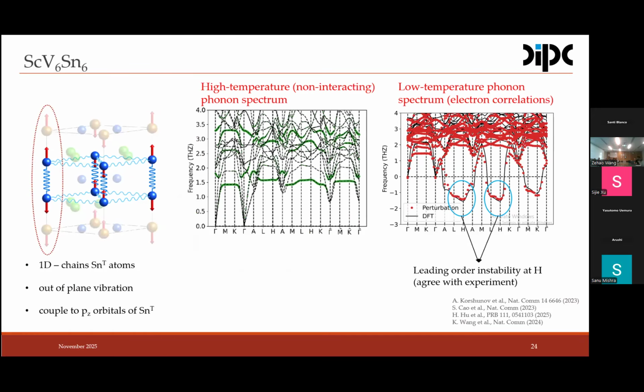We can put a bit of theory here, a bit of calculations by the group of Andrei Bernevig. We identified this soft mode as an out-of-plane vibration of the trigonal tin. Here I show in this sketch the unit cell of ScV6Sn6, highlighting the Kagome plane with the tin moving up and down along the z-axis. So this is like a Peierls chain where the trigonal tins move out of phase along the z direction. At high temperature, and by high temperature I mean electronic temperature of several thousands of Kelvin, this mode is nearly flat. But when we switch on the electron correlations, the electron-phonon interaction, we see how the phonon becomes negative and imaginary at the H point.